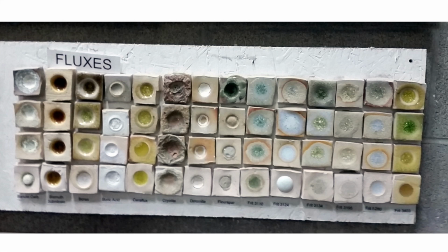This image shows a fusion button test tile display for the flux ingredients. Back then we tested Custer feldspar 100%, then Custer feldspar 90 with whiting 10, and then 80-20, and so on. They were fired to different temperatures. So that's way too much work for me. And more importantly, who would ever apply a glaze like that?